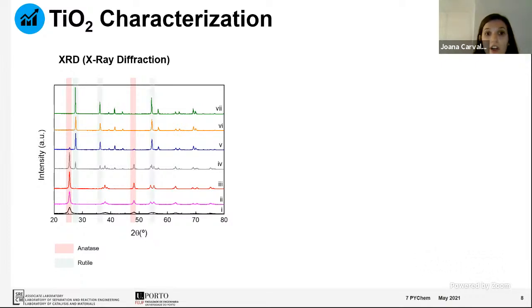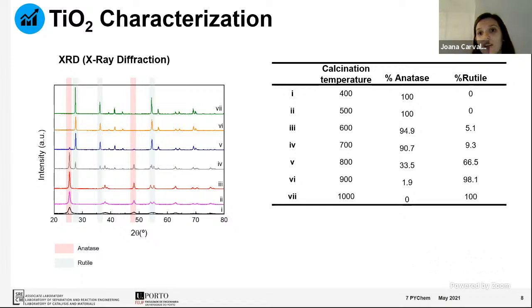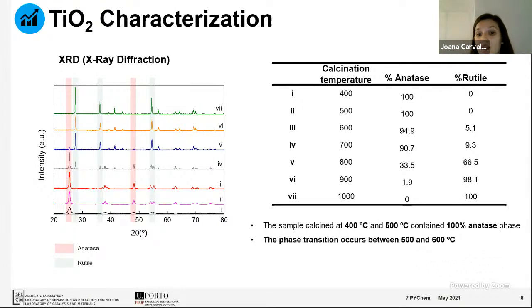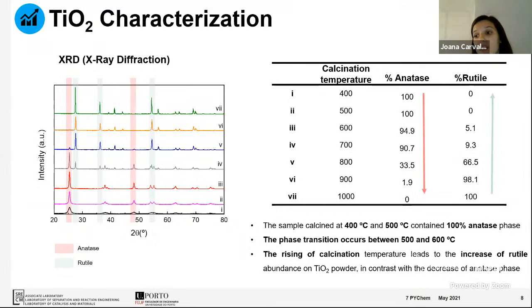The same happens here. With this information, we can calculate the quantity of anatase and rutile present in the samples, and we can observe that the materials calcined at 400 and 500 degrees contain 100% anatase. The phase transition occurs between 500 and 600, and we can conclude that with an increase of calcination temperature, the anatase phase decreases and the rutile phase increases. This difference of phase will in fact affect the photocatalytic activity of the material.